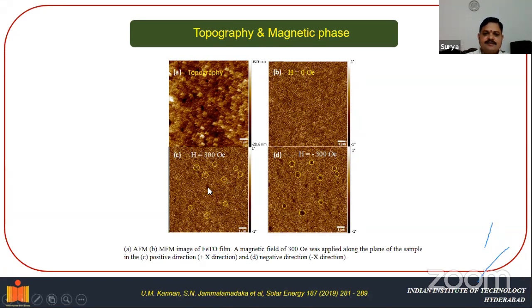the magnetic phase, what we have done is initially we have applied 300 oersteds, positive 300 oersteds. What we could see is a bright contrast, and when we reverse the magnetic field to minus 300 oersteds, the same bright contrast has been transformed to the dark contrast. What does it mean? It means when we apply the magnetic field of 300 oersteds, all the magnetic moments within the nanoparticle saturated in one direction, which leads to the bright contrast. And when we apply negative 300 oersteds, the magnetic moments are oriented in the opposite direction. This leads to dark contrast.